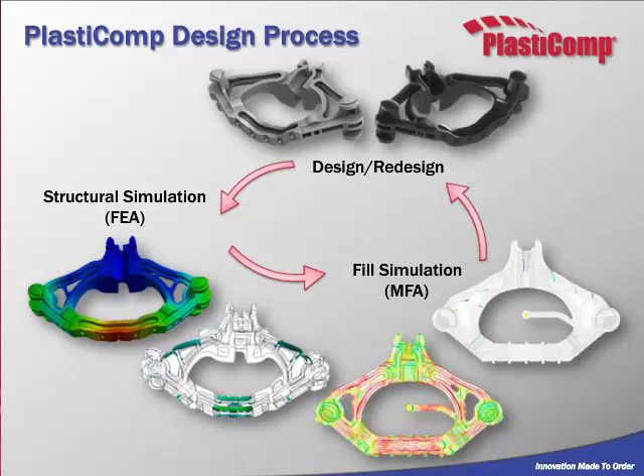So on the top is that example of the crossbow riser. What we want to look at is a mold flow. We'll run a mold flow simulation to see how fiber is flowing through your part and where your weld lines are, and we also want to run an FEA. We want to find out where the highest stress sections of your part are. You want to make sure you don't have any weld lines in those high stressed areas, and in fact you want to have a better fiber orientation there. So it's really a triple play between your design, your moldability, and your stress analysis, which we'll walk you through.